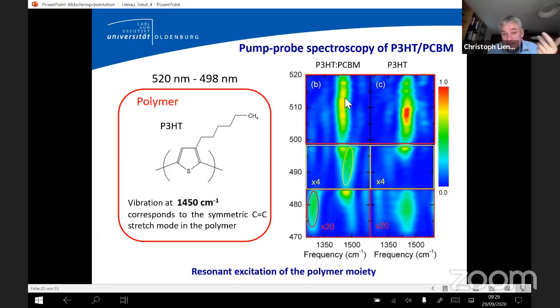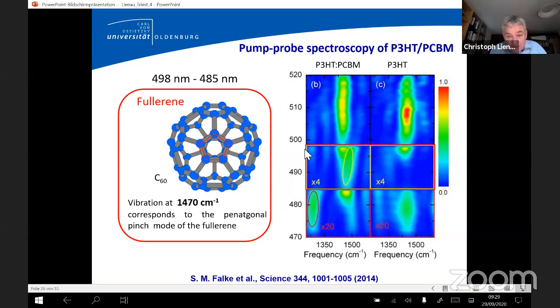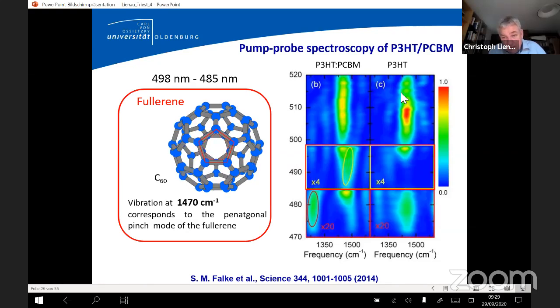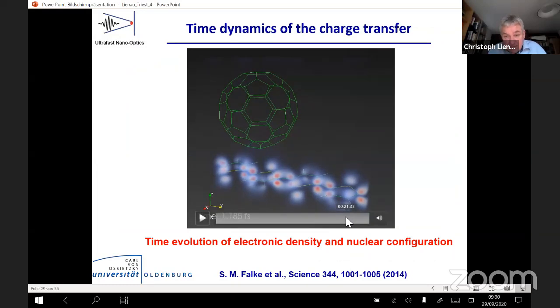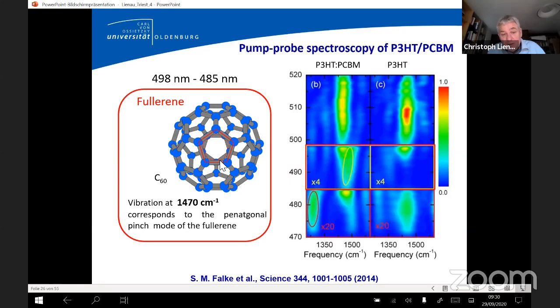This is happening as expected, both in the blended film containing C60, but also in a regular polymer film containing no C60. So it just means that the light pulse impulsively excites the polymer, and in response to the optical excitation, the polymer does this. But what is more interesting and what was puzzling is the response in this region between 490 and 500, say. Because here, there's no vibrational action in the polymer itself, but if we fill in C60, we see that the system now oscillates at a different frequency. If we look at it carefully, it's 1470 wave numbers, and 1470 wave number is the pentagonal pinch mode of the fullerene ring.